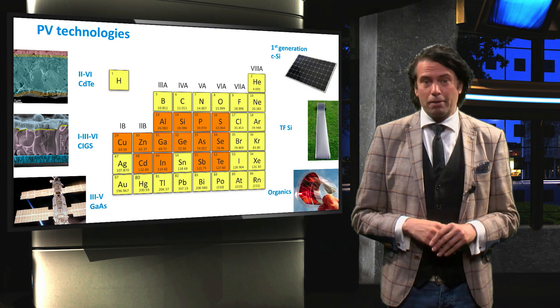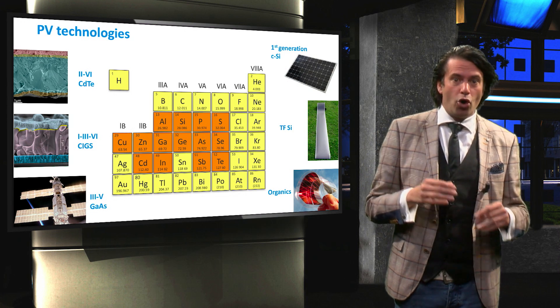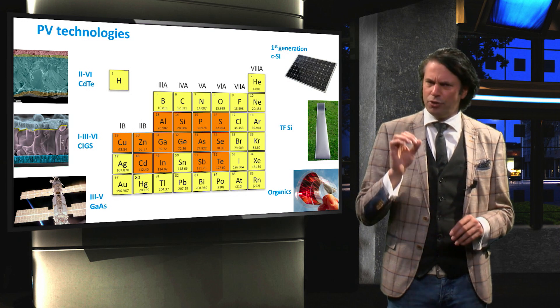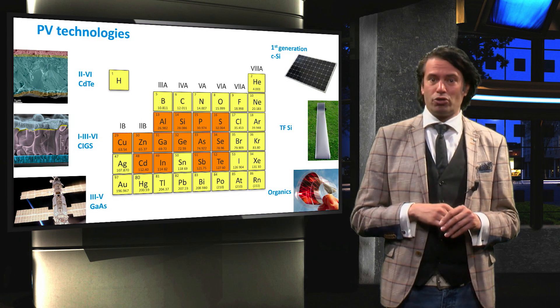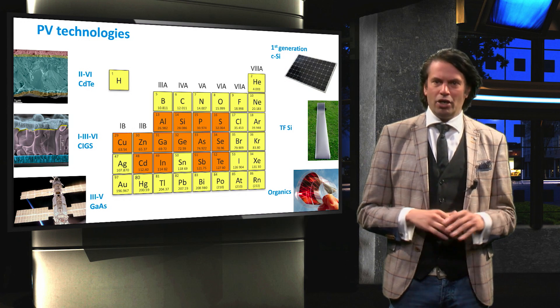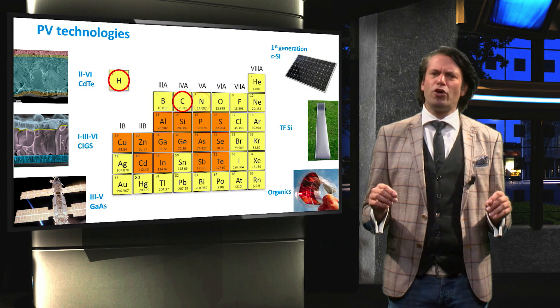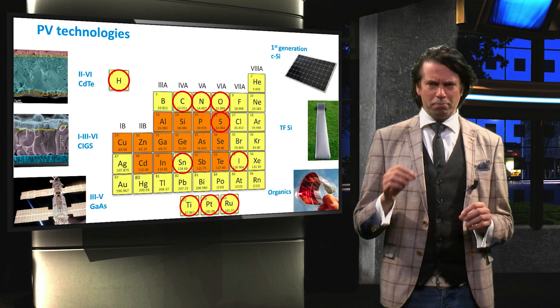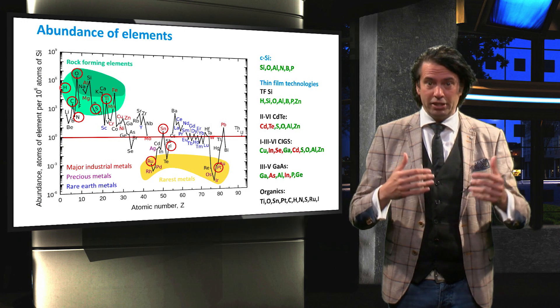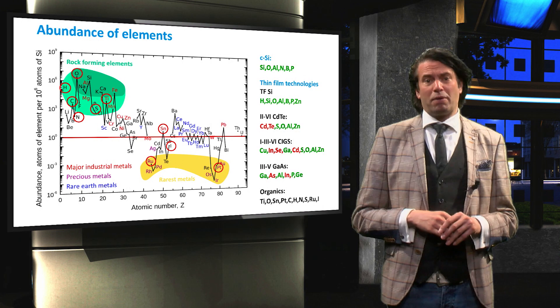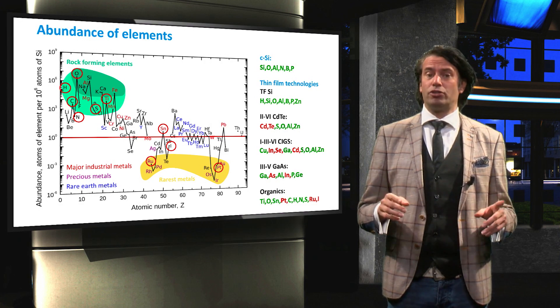Finally, we will consider organic PV technologies. For organic PV, the used absorber materials are either conductive organic polymers or carbon-based organic molecules. In the organic PV section, we will also discuss hybrid organic-inorganic PV technologies such as the dye-sensitized solar cells and the perovskites. A wide variety of materials are used for organic PV from different groups. Generally speaking, even though organic solar cells themselves use cheap, abundant materials like carbon, they require expensive encapsulation materials and contacts to protect the organic materials from humidity, moisture and air. Some of these materials like platinum, ruthenium and iodine are very rare. This constraint limits the industrial application of organic PV.